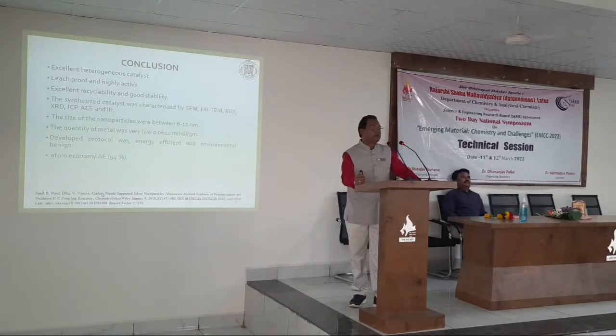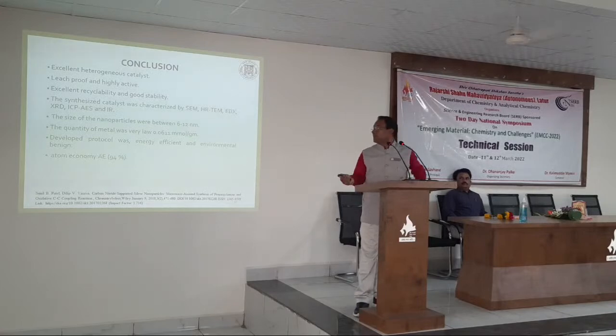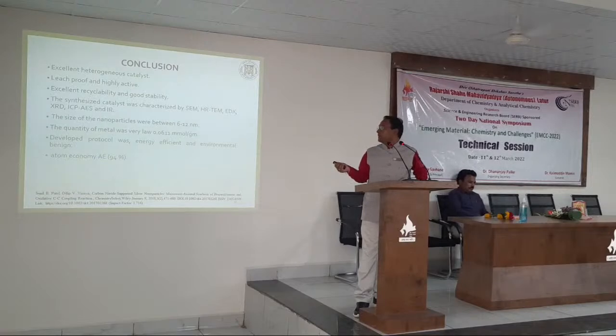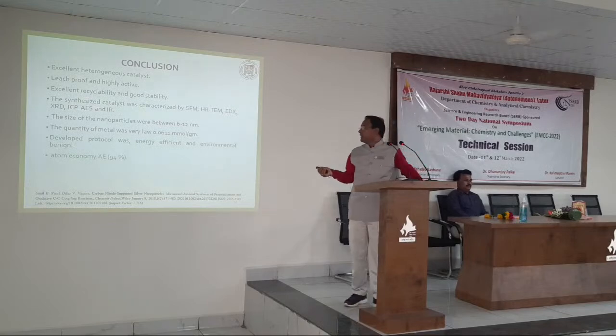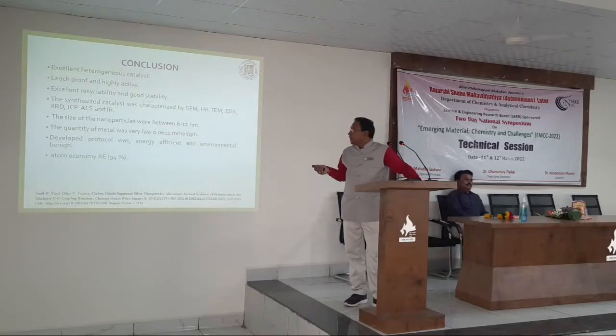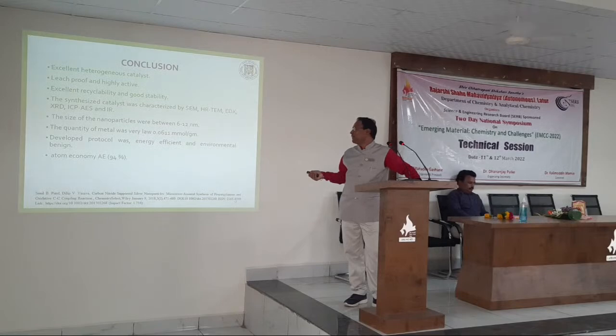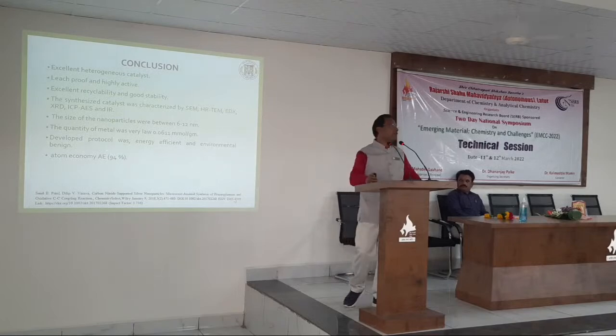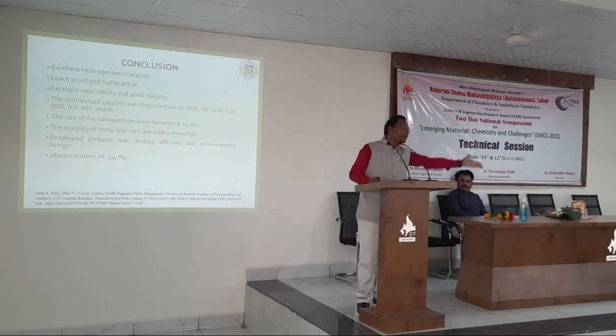So in short, the finding here is that we have a heterogeneous catalyst. All these methods were utilized to characterize the work. The size of the nanoparticles was found to be 6 to 12 nanometers, and this was the quantity of the nanoparticles taken: 0.0611 millimole per gram, and the atom economy was 94%, because all the atoms should convert into the product.